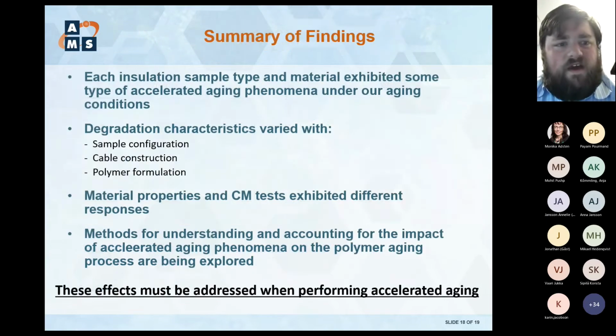So the summary of what we found: everything we've been testing at the conditions we're at, depending on the sample type and material, exhibited some type of accelerated aging phenomena. Degradation characteristics really varied depending on sample configuration, material type, and cable construction. You can see how these different phenomena had a significant impact on material properties and CM test results, and each different type of CM test exhibited different responses.